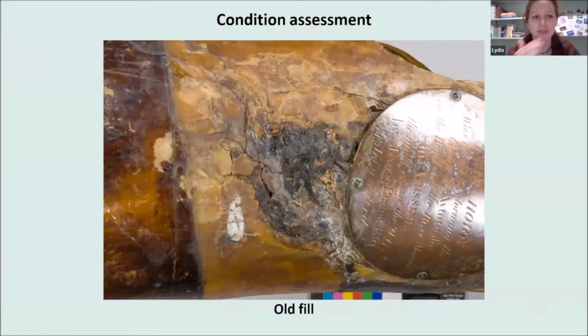With the removal of the bandages, I also uncovered another repair we weren't actually aware of. A large fill comprised of dark resin and a top layer of wax is located next to the plaque. The filling material was starting to deteriorate, with layers of wax delaminating from the horn surface and exposing the dark brown resin. The resin itself was cracked and started to separate from the horn material as well.